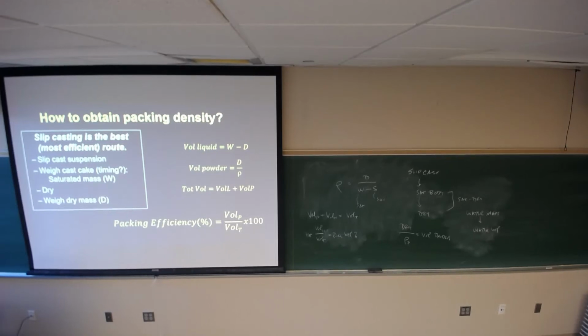If I cover my cast, right, and prevent free evaporation from the surface, what should happen is once I'm done casting, my water loss is very shallow. My water loss versus time is shallow. And I have somebody working on that now. Somebody here working on that? There's somebody in 314 working on that. Okay? How fast does water evaporate from the sample? If you look at Rehan and Hunter Pryor's thesis, they didn't do that. Their water loss is rapid. Okay? But what you're looking for is then at what point you hit saturation and then dry the sample.